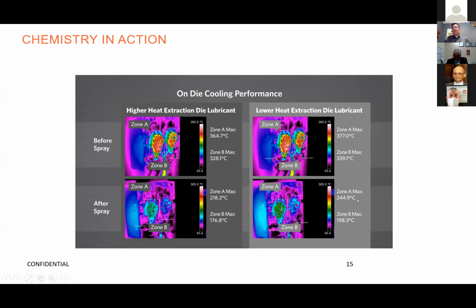So instead of targeting a 244 degree post-spray temperature, with the higher performing lube we would take that up to 275 or 300 degrees, because the product itself was still effective in protecting the die. There's something about the chemistry on the die surface that's better for solder protection, better for release and slip, whatever else you need, metal flow. And that's where another aspect comes into play: die life.